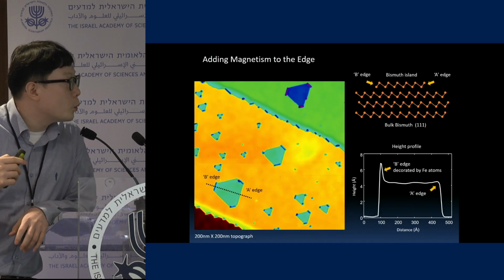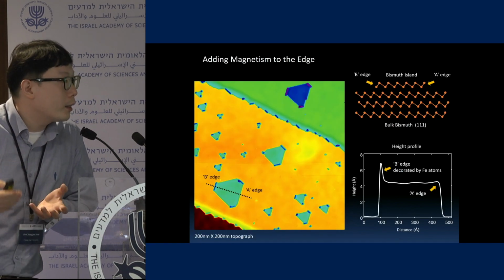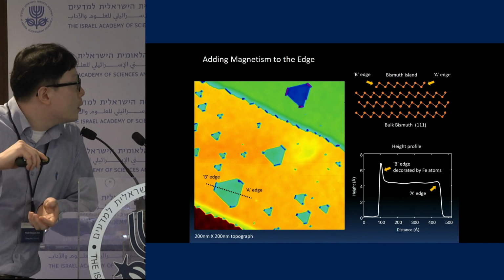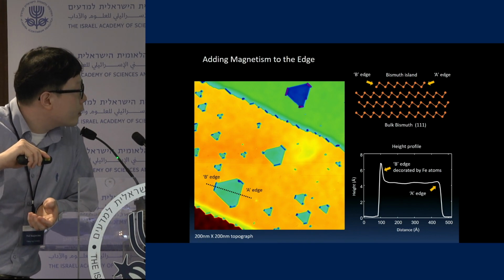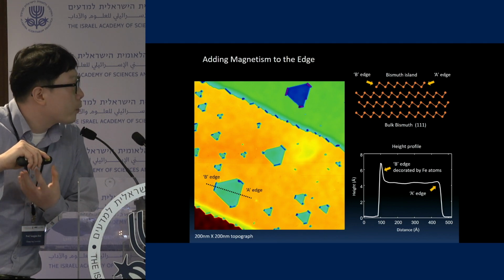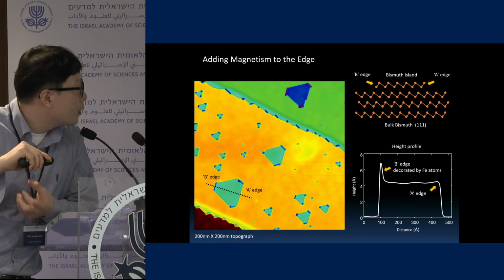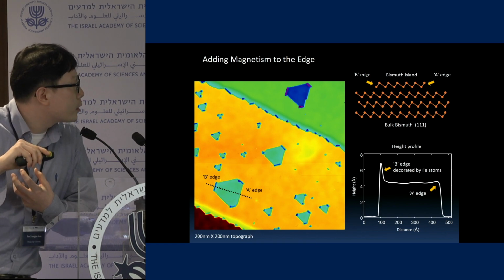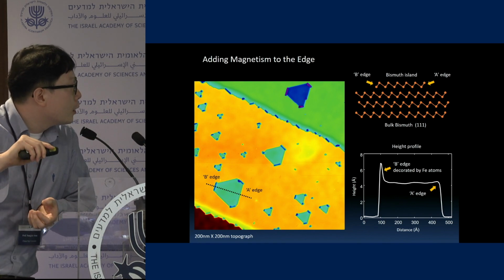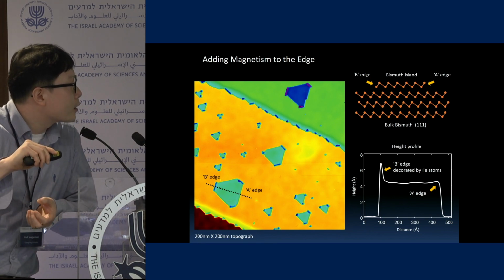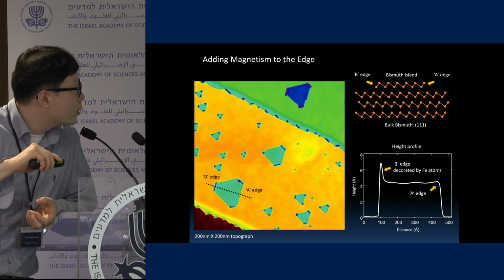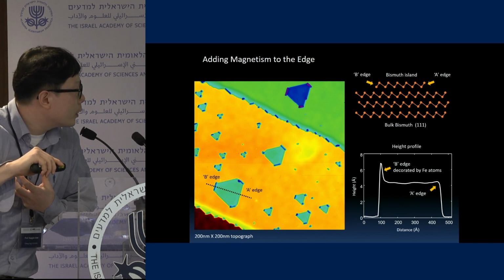The next thing is we wanted to terminate this helical edge state superconductivity. So this is an island made of bismuth films, and we evaporate iron on it, and interestingly, iron is decorating only the B edge side, which is very strongly hybridized, or topologically the hinge state does not exist in there. So this is a good one-dimensional state, located here, very well localized. Then we induce superconductivity on here, and it's very well terminated at both ends.